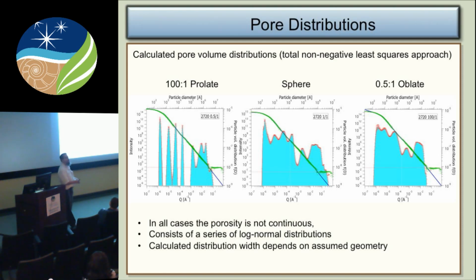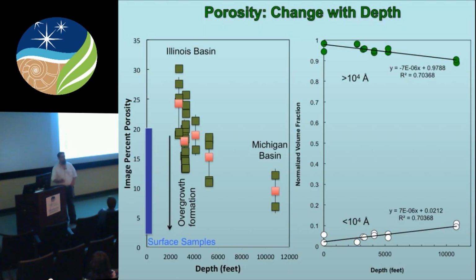But to occur in a series of distributions. And it turns out, it was actually suggested long ago by work on sandstones just by sieving them, that sand grain distributions were log normal. And essentially that's what we seem to see here, a series of log normal distributions, somewhat smeared out, and we can't exactly tell the difference between those.